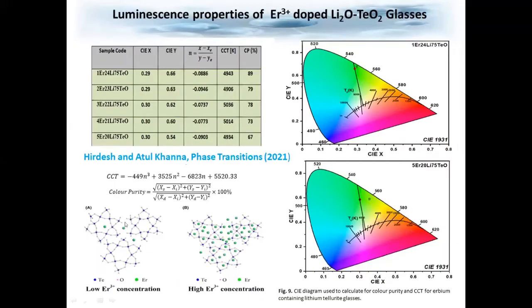So this is the picture of the structure. When the concentration of erbium is low, they are occupying these voids in the glass network. But when the concentration is very high, they fill up the voids, and there is a very large number of erbium ions near each other in a small localized region. That increases the probability of non-radiative transitions, and that is why you see concentration quenching effects.